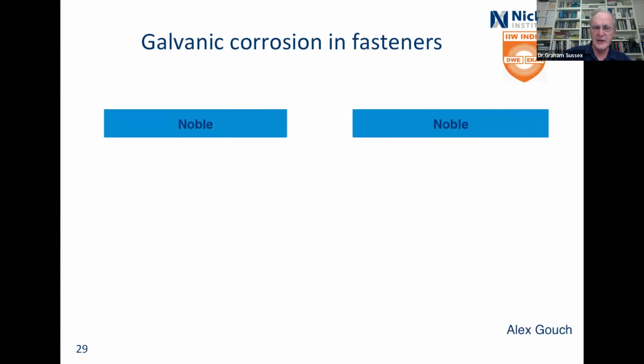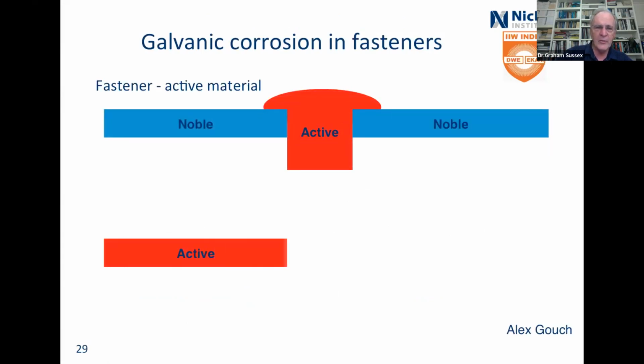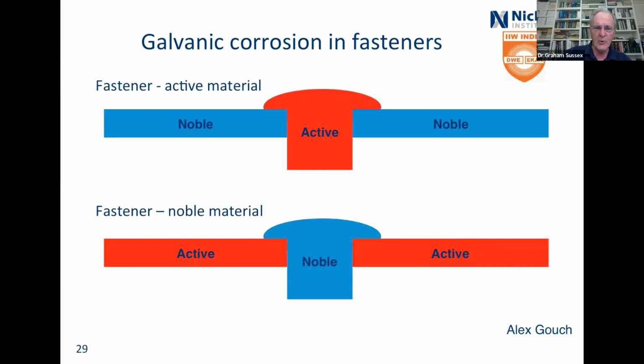So in fasteners, this is a little model. We've got fastener active, fastener noble, and what's going to happen? It's going to corrode like that, it's going to corrode like that, and it's going to fall out. That's not good, okay? So what this is saying is that fasteners should always be the more noble material. Then you can get some corrosion either side, but that's not going to be really a problem. Except that if you weren't too careful about putting it in and it doesn't fit too well, then you can wind up corroding away the active material next to it, and you get a loose bolt, and eventually the loose bolt falls out.